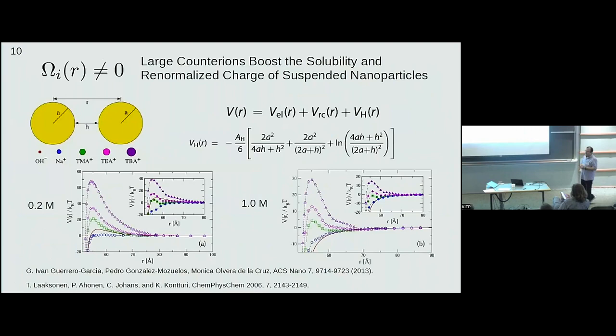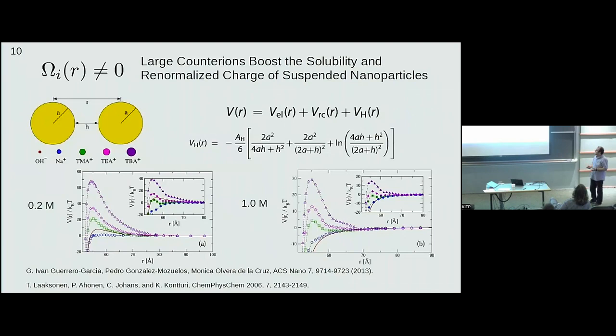This attraction occurs at a range beyond ion bridging. In a simpler model with only charged colloids, we have also observed the phenomenon of ion bridging when the salt is asymmetric and at very large concentrations. Another interesting experimental observation: coated nanoparticles that are negatively charged in the presence of sodium hydroxide — at concentrations below 0.2 molar the solution does not coagulate, but at 0.2 molar all negative particles coagulate experimentally.